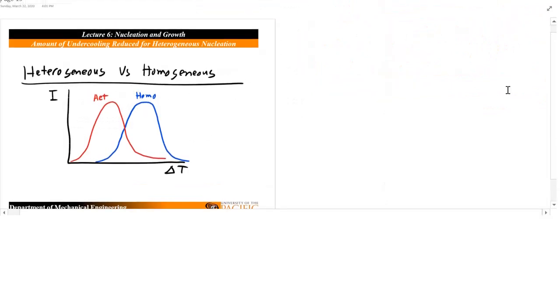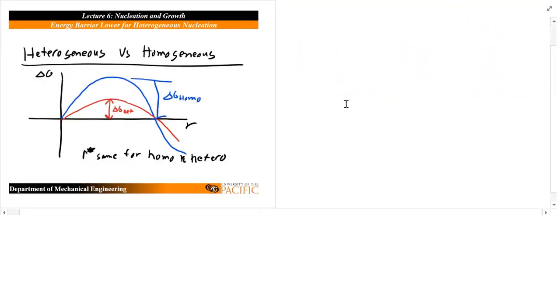We can see that much more clearly up here, this is essentially the curves for heterogeneous and homogeneous nucleation. And you can see here, the R star value, R star is the same for both of these. The only thing that changes is the energy barrier. It's much harder to nucleate particles for homogeneous nucleation versus hetero.